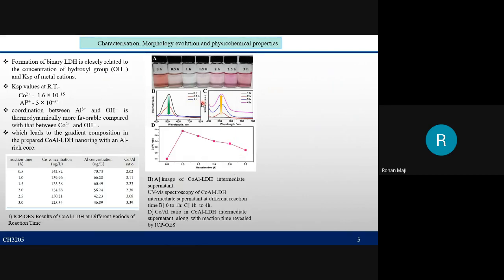At 1 hour reaction time, the nearly zero absorbance of cobalt 2+ indicates the full interaction between cobalt 2+ and OH- to form the LDH structure. After that, the hydrolysis of excessive urea led to dissociation of the core. Then again, the concentration of cobalt 2+ increases, so absorbance gets higher and the color comes back.